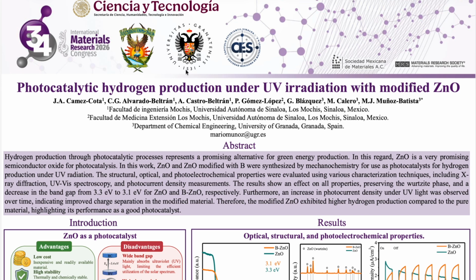Granada, Spain. Abstract. Hydrogen production through photocatalytic processes represents a promising alternative for green energy production. In this regard, zinc oxide, or ZnO, is a very promising semiconductor oxide for photocatalysis. In this work, pure ZnO and boron-modified ZnO were synthesized by mechanochemistry for use as photocatalysts for hydrogen production under UV irradiation. The structural, optical, and photoelectrochemical properties were evaluated using various characterization techniques, including X-ray diffraction, UV-vis spectroscopy, and photocurrent density measurements. The results show that boron modification affected all the evaluated properties while preserving the Wurtzite crystal structure. In particular, the band gap decreased from 3.3 electron volts for ZnO to 3.1 electron volts for BZnO.